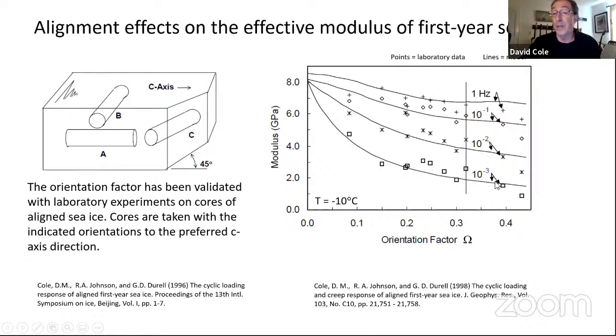So we're engaging more of these anelastic mechanisms here. We get more and more anelastic strain, and we see the anisotropy get quite a bit stronger for oriented ice when there's a lot of dislocation. So that's what omega does. You'll see that pop up. We've seen it in all the calculations so far.